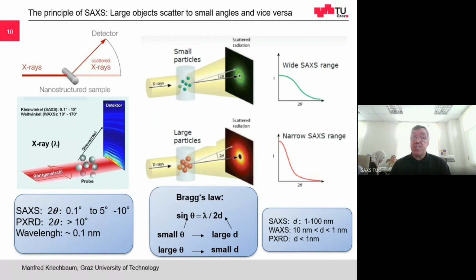Okay, so let's go back to the principle. The principle of small angle X-ray scattering. The underlying mathematical formula is Bragg's law. Bragg's law basically says that the scattering angle of your scattered X-ray is inversely proportional to the nanostructural size. The sine of the scattering angle equals your wavelength divided by the size of the nanostructure. This means it's inversely proportional, that small particles scatter to large angles, and large particles scatter to small angles. And we are focusing on small angles, or focusing on the large particles. So we have to use small angle X-ray scattering, and not powder X-ray diffraction.